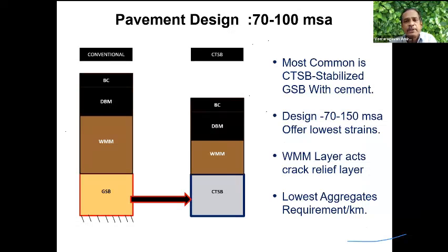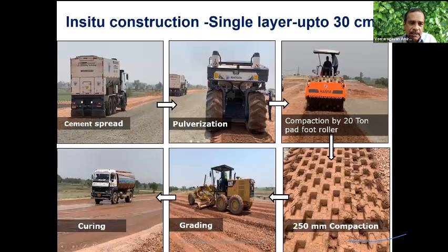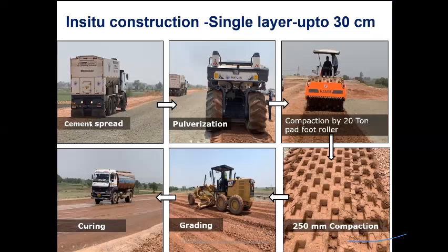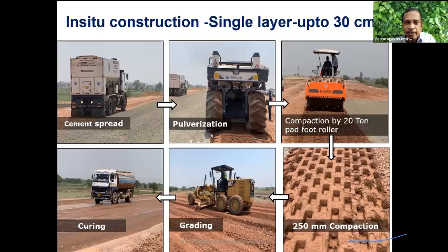For a design life of 70 to 150 MSA, the wet mix macadam, which I'm providing here, acts as a crack relieving layer. This crack will propagate to the top. So you should know the problem, you should know the solution. But you can find the thickness reduction is significant. It's possible here. I can quantify and show here. So what I do here is the cement is well-known product. You spread, I don't require a huge quantity of cement as well. 2%, 3%, 4% may be adequate. You spread the cement, pulverize the material, compact it in layers, grade it and cure it over.